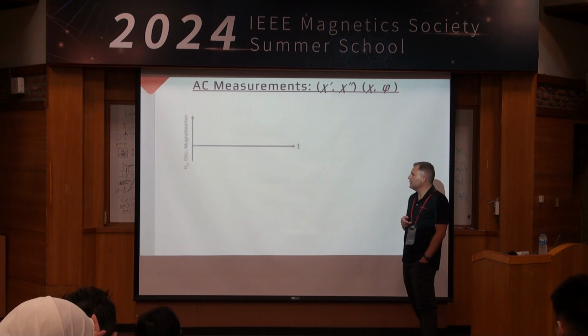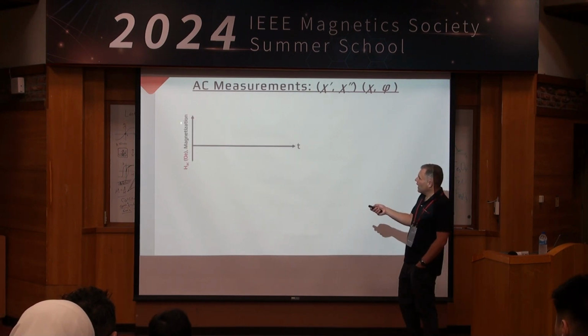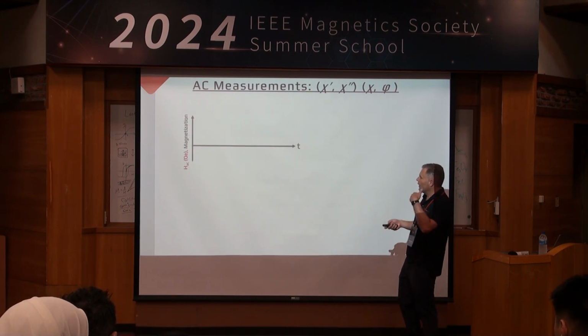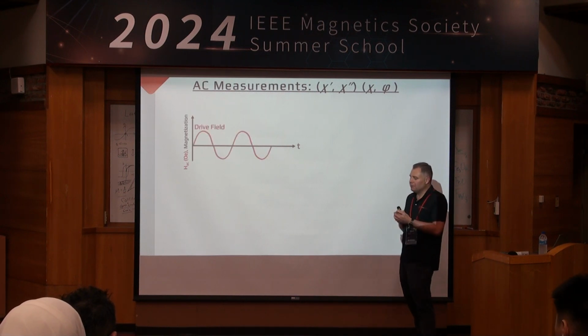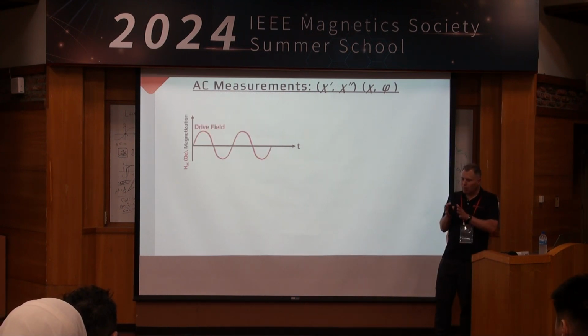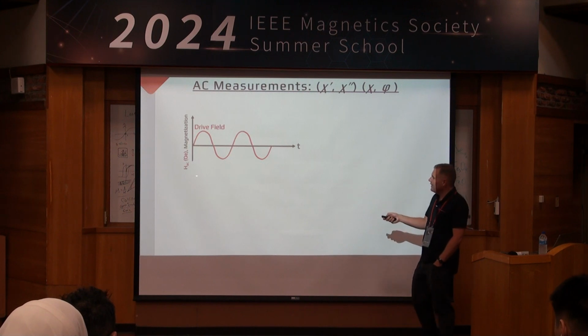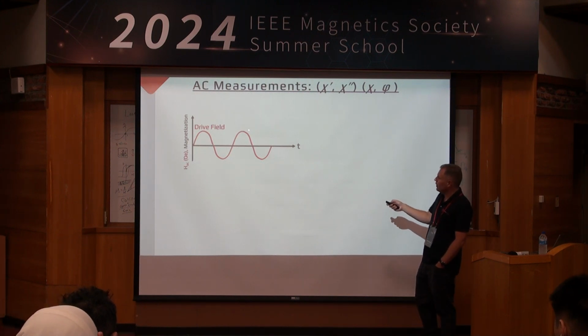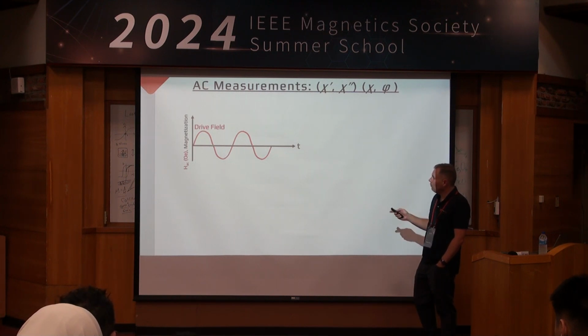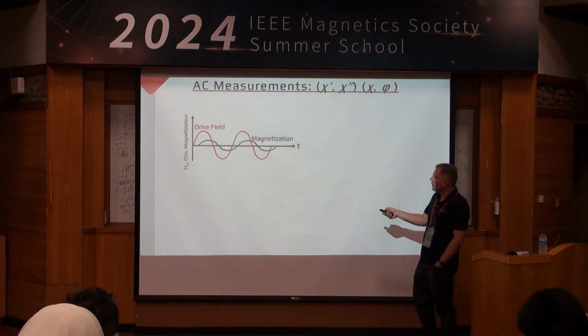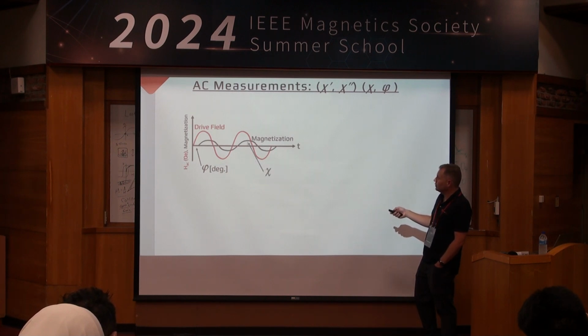So how do we actually do an AC measurement? On the y-axis, I'm going to have the AC magnetic field. We have an AC drive. Usually AC measurements are done at a small or sometimes zero DC magnetic field, or sometimes even a large DC magnetic field. But the thing that's most important is the AC magnetic field. We come in with a known amplitude and frequency, and then we just measure how the magnetization varies in response to that AC field. In general, there's going to be some sort of a phase shift and an amplitude to this response.